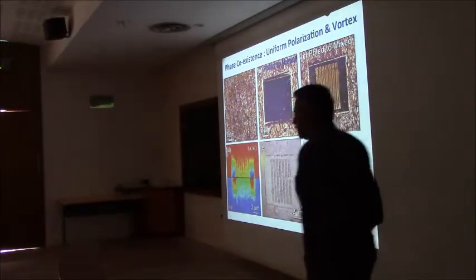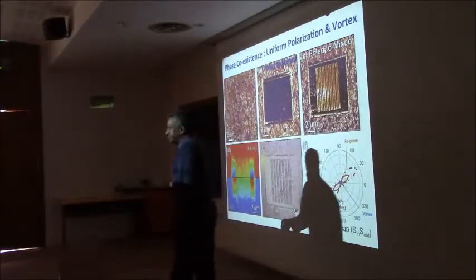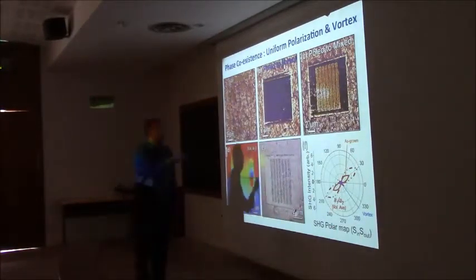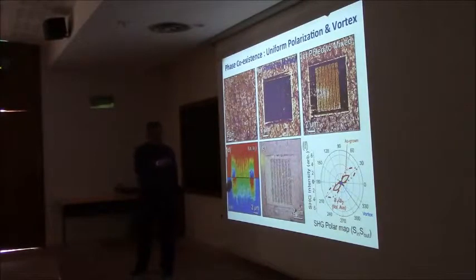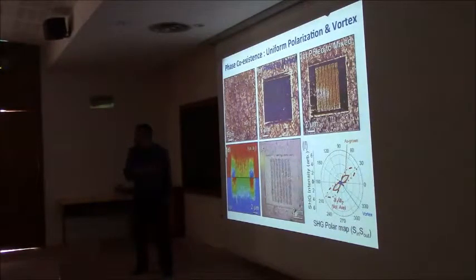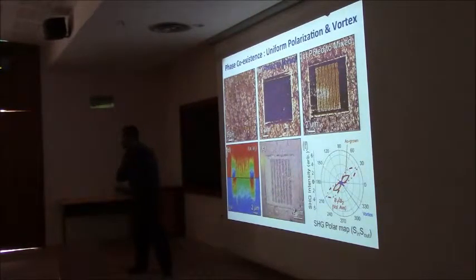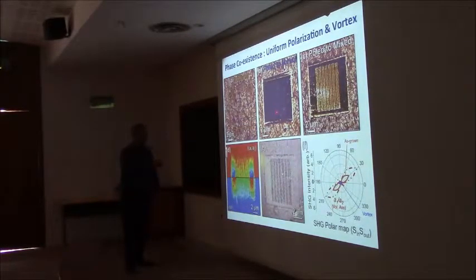we can switch portions of it completely to the vortex phase. Then you say, hey, how did you know that's the vortex phase? You can go back and do micro diffraction, electron diffraction. No, sorry, X-ray diffraction. And indeed, you can pick up the structure of the vortex phase. The out-of-plane lattice parameter for the vortex phase is slightly larger than the ferroelectric phase because the C-axis is in plane for that. Then I can go back.